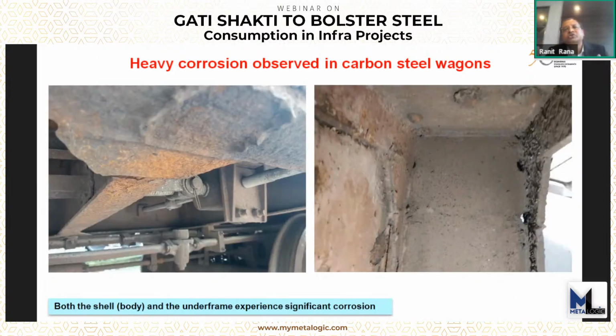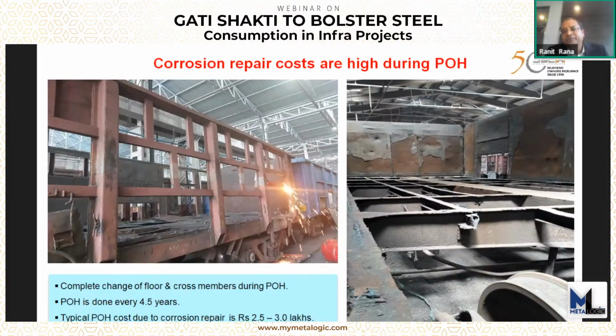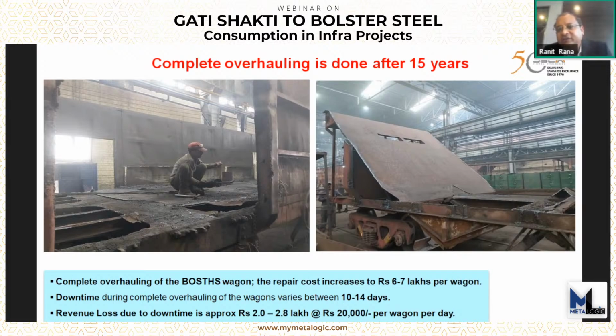And this corrosion is prevalent not only on the body of the wagon, that is the shell, but also on the underframe. And as you can see, the corrosion eats away the entire material, and that makes it extremely dangerous to operate. And what we found out was that during the periodic overhauling, which happens after every 4.5 years, the corrosion cost is significantly higher. It varies from 2.5 to 3 lakhs per wagon. And after 15 years, when the wagon needs to be completely stripped because of corrosion, this cost increases to 6 to 7 lakhs. And normally the downtime because of this corrosion repair comes to about 10 to 14 days.